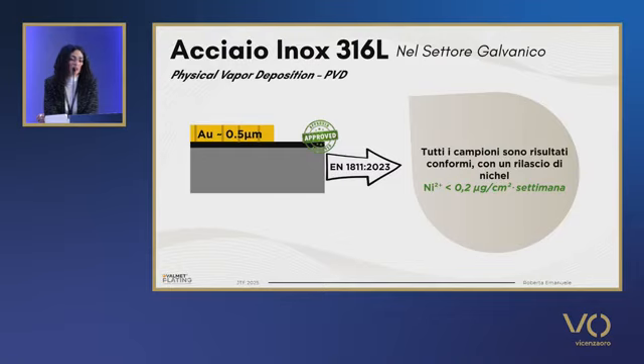prepared using PVD technology, physical vapor deposition. So we put gold on the steel without removing the oxide, and we deposit only on one side, leaving one part non-covered. So we tested the samples, and all turned out to be within the limits as set by the legislation.